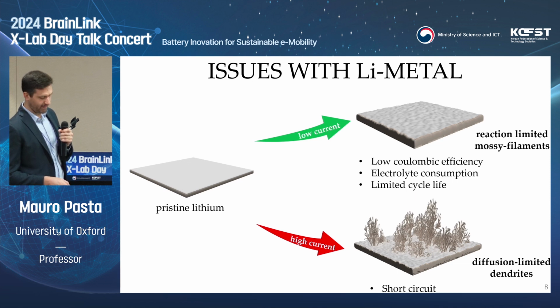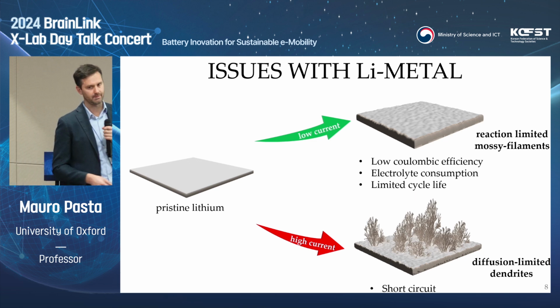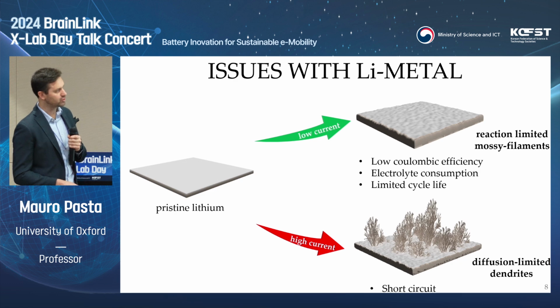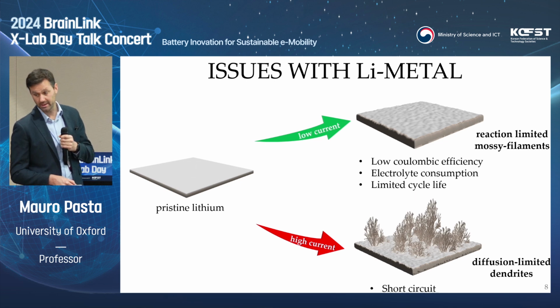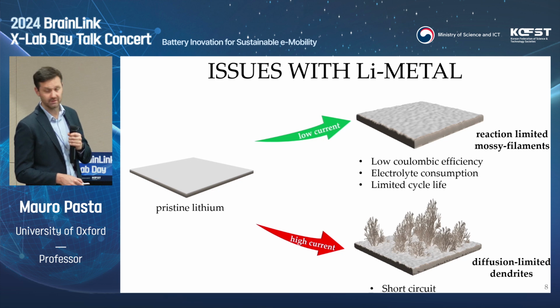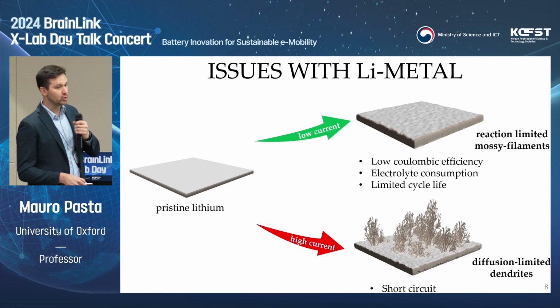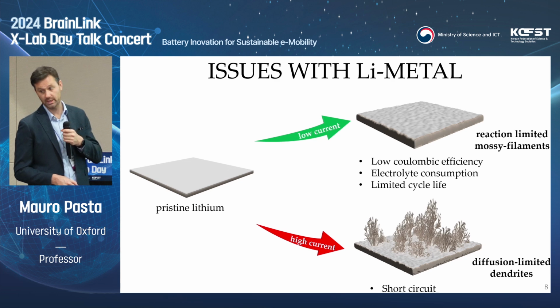You can, in principle, operate at lower current densities. You can charge at a lower current density. You can do that, for example, in some of the aviation applications that I mentioned earlier. But still, even if you charge at a lower current density, you're often in this reaction limited regime where high surface area lithium, which is often referred to as mossy lithium, so not necessarily dendrite, but high surface area lithium, still forms. And that leads to new lithium surface being exposed with the formation of new SEI, low Coulombic efficiency, you consume electrolyte, and ultimately you limit your cycle life.